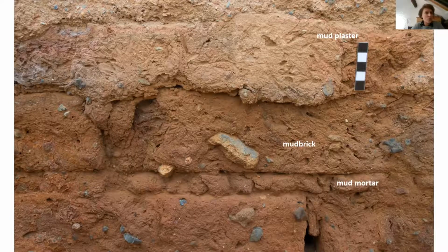Where it is preserved, the mud plaster is composed of a sediment matrix ranging from red to reddish yellow with large quantities of straw, up to 60%, in stalks 3 to 10 centimeters long. The incorporation of straw in the mud plaster matrix reinforced the structure of the coating. It also reduced the risk of it shrinking and cracking by helping the drainage of excess water outside the mud coating. Only in some rare instances were seagrasses identified in the mud plaster, where their presence seems accidental.